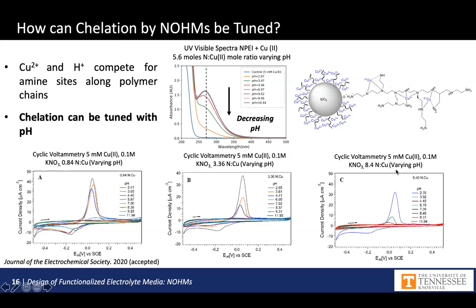And if we look at the electrochemical study, we see exactly the same thing. This is 3 different studies with different ratios between the amines in the chains and copper. And we see that for all the ratios, as we lower the pH, we see the appearance of the electrochemical signals. So again, this suggests that the chelation of these copper ions by the molecule can be tuned via the pH.